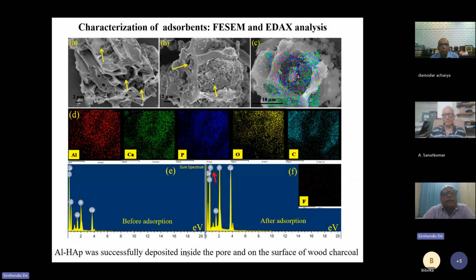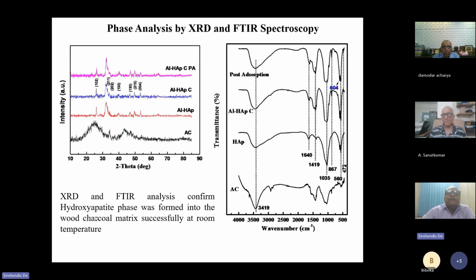Then we characterized the adsorbents with FESEM and EDX analysis. It is clear that this is the carbon scaffold I was talking about, and inside the carbon, the hydroxyapatite phases have been generated, and those are the potent sites where the fluoride gets adsorbed. If you look into the EDX curve, there is a peak of fluoride after adsorption, which was not there before adsorption. So this proves that the fluoride is being adsorbed within the media. Phase analysis using XRD and FTIR spectroscopy shows the signatures of the presence of aluminum hydroxyapatite inside the carbon.